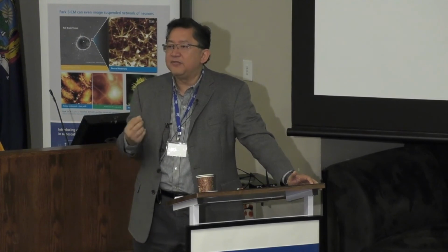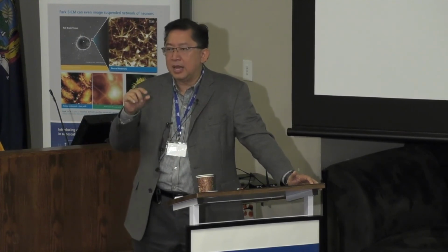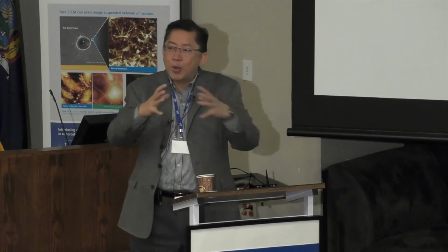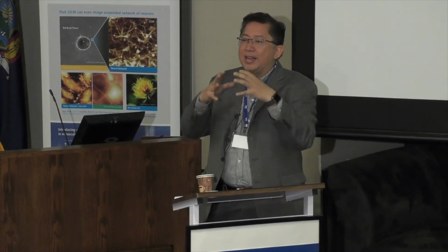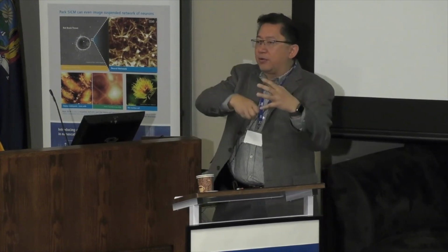So what we emphasize is very thin surfaces, very thin films, anywhere from a few nanometers to not more than 50 nanometers. The other thing is the conducting polymer changes the swelling behavior of those cavities. So when we reduce them, they swell in the solvent, they grow bigger, and therefore release the molecule or the template faster. And then when we oxidize them back, it contracts to the original size. So the key to that, and we have a patent on that, is manipulation during the preparation with a solvent and a bias voltage. So you can have very high efficiencies. I like that question. Yeah, very important.